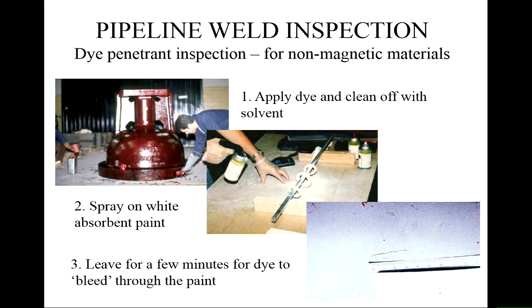And I mentioned you need to be able to measure things. You can measure the length of the crack just by putting a ruler against it, which is very useful. So this is a commonly used factory inspection technique. You know, the skill level for the inspector is pretty small. They need to be able to paint things, and they need to be able to read things off with a ruler. The key thing is leaving it long enough, a few minutes as it says here, for the paint to be sucked out so that you get these marks. If the surface is very rough, you can't always see it, but painting it white with these spray paint systems gives you a fairly good visibility of what you're looking at.